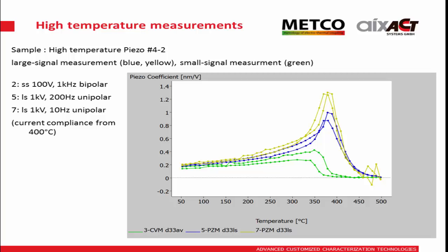And this is a measurement taken on the bulk material, on the high temperature materials. And what you can nicely see here, this is actually an extreme case on this composition, that large signal measurements are now here in blue and yellow at 2 different frequencies. It's 1 kilovolt, and yellow is 10 hertz, blue is 200 hertz. And we can see at the high temperature that the large signal, which comes from a triangular excitation, is actually much bigger than your small signal, which is shown here in green, which is still 100 volts, so it's not really small, but we can see much different behavior.